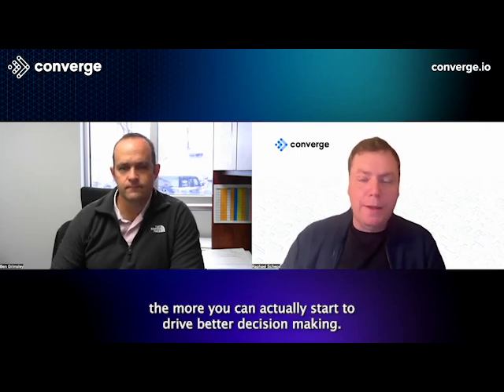Yeah, for sure. So I guess that's back to the blending of cost and carbon, because you can maintain your productivity levels or even go faster and still use a low GWP mix on that project in the right environments, at least. Yes. And actually, what we've certainly seen is if you take GGBS-based mixes, there's much higher temperature sensitivity than regular Portland cement mixes, which means in high temperature environments, they cure really quickly. In low temperature environments, obviously, they cure quite slowly, which has been a challenge for the industry. So I'm totally with you there, the more data you have on the millions of mixes out there and the different recipes, the more you can start to drive better decision making.